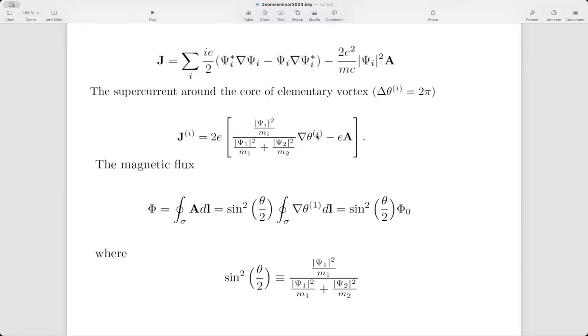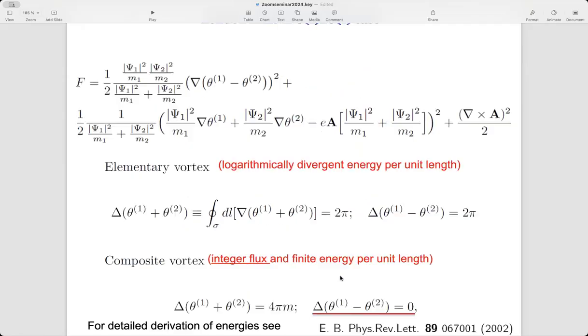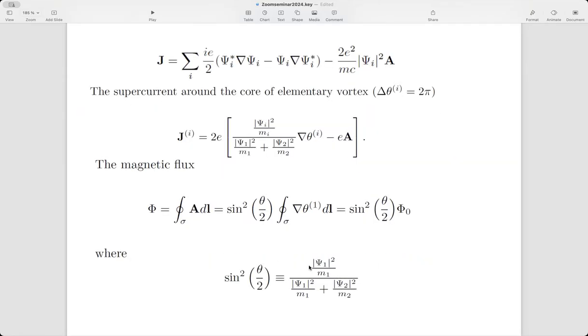And then one does a vortex magnetic flux argument. One expresses the vector potential through everything else and integrates it over a closed path around the vortex. And then one can see that such a vortex carries only a fraction of the magnetic flux quantum. This vortex no longer carries a magnetic flux which is a function of fundamental constants only, but it can carry an arbitrary fraction of the magnetic flux quantum, which is just given by the ratio of these fields.